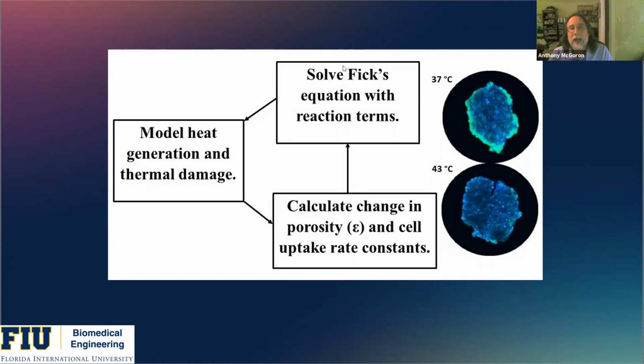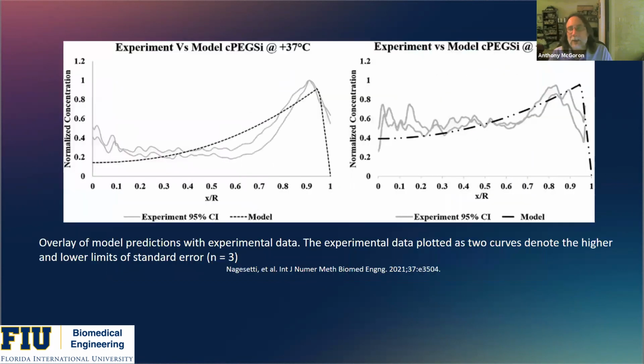Then we used Fick's law equation with reaction terms and iteratively optimized the model to derive the optimal characteristics, the optimal parameters that govern the diffusion of these nanoparticles through the extracellular matrix and interaction with the cell and uptake into the cell.